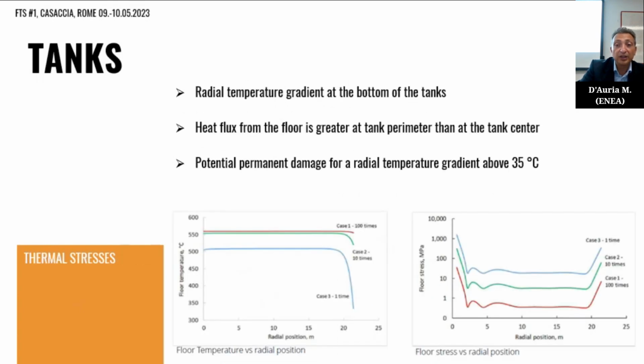Another issue at the floor of the tanks are thermal stresses, because near the center of the tank, thermal resistance to heat transfer from the floor to the foundation can be greater than the thermal resistance at the perimeter of the tank. So heat flux from the floor is greater at the perimeter than at the tank center. Simulation shows that any radial gradient above 35 degrees is sufficient to permanently damage the floor.